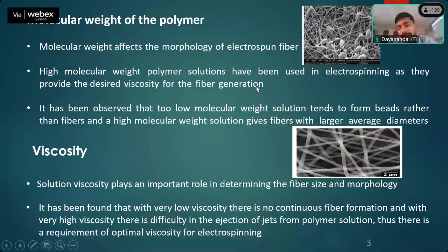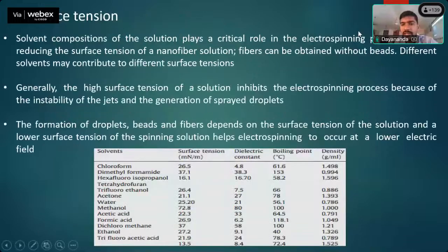It has been found that low molecular weight solutions tend to form beads rather than fibers, and high molecular weight solutions give better average fiber diameter. These are some images of nanofiber mats where we can see bead formation, because whatever molecular weight was taken was not suitable for the proper electrospinning process.